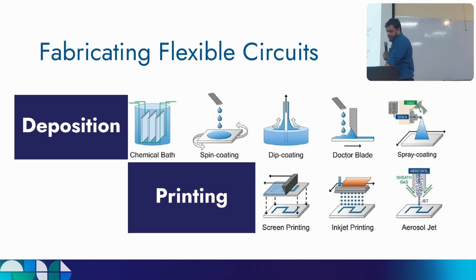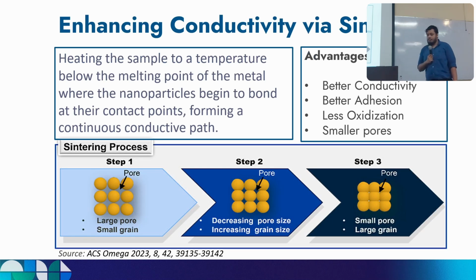After printing those electronic circuits, we have to do a process called sintering. So what is sintering? Let's say those metallic inks that we use, they have organic solvents in them. Those organic solvents are not conductive, therefore they hinder the metal's ability to conduct electric signals. So we have to heat our samples, that means our circuits, locally or using some method below the melting point of the nanoparticle inks, so that the bonds are stronger. That means the metallic bonds become stronger.